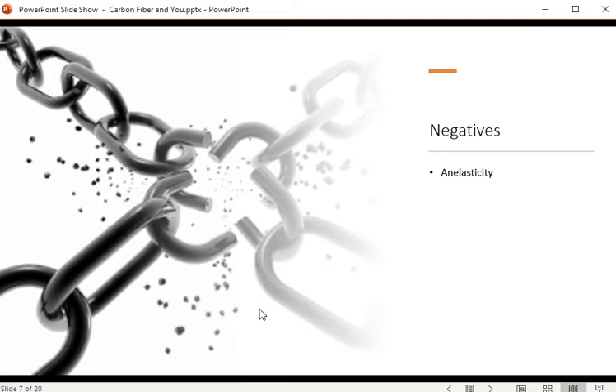It's typically measured and analyzed by testing the percent elongation a standardized material sample has, commonly put into a dog bone shape, before it breaks. In this instance of a pure carbon fiber sample, it typically takes less than 2% elongation before fractures occur. This is according to ASTM's analysis. While carbon fiber tends to be resistant to most causes of elongation in an application, in the case it does occur, it will likely lead to a quick and brittle failure, which in most engineering applications is very undesirable.